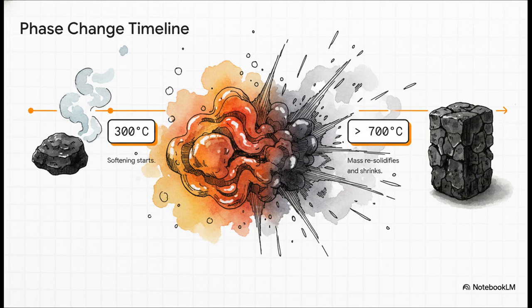Then, entrapped volatile gases are forcefully released before the entire mass resolidifies and shrinks into a final, hard, porous coke structure right around 1100 degrees.